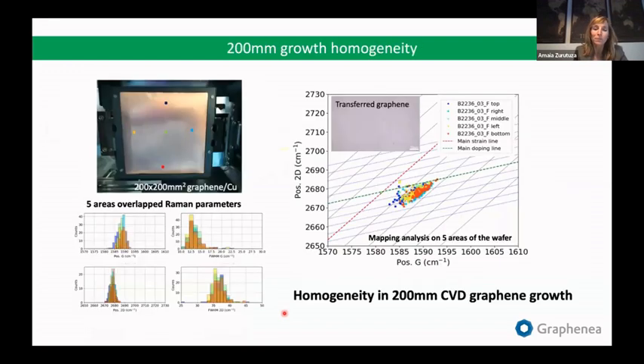Okay, for the quality control, we need to use a plethora of methods, but Raman spectroscopy, as you know, is very relevant for carbon materials, and we do it routinely. We do it on 200 millimeters. As you can see here, we do different areas, typically top, bottom, and in the center. We get statistics to see that the growth is under control, and we are getting always the same.